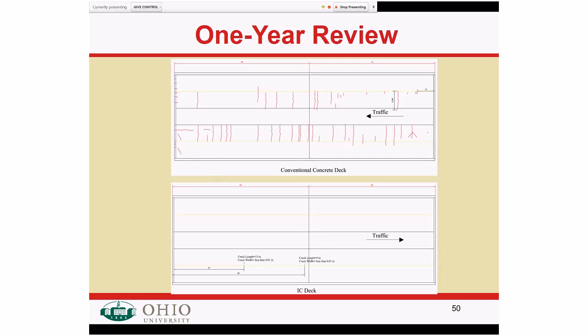We went back a year later and we counted cracks. And you can see from the top image, the conventional deck had a fairly typical distribution of cracking, mostly near the middle of the panels, and nothing too crazy, but quite a lot of cracking. Then you come down to the internally cured deck, and there's two very small cracks.